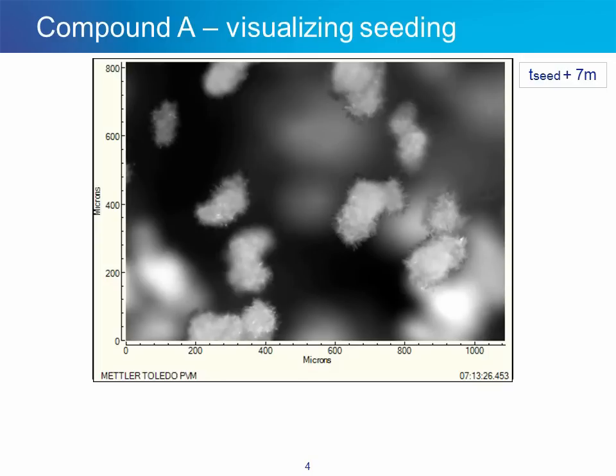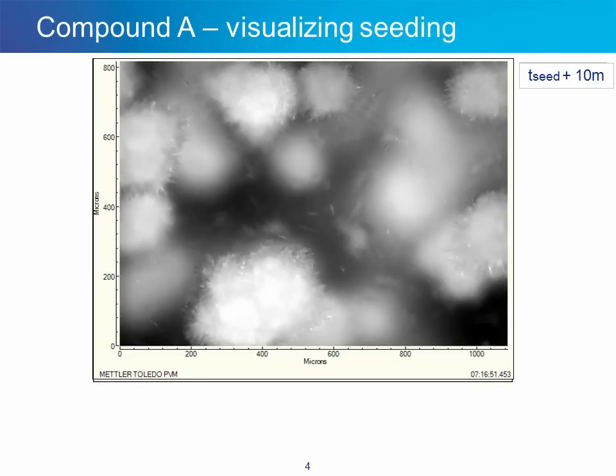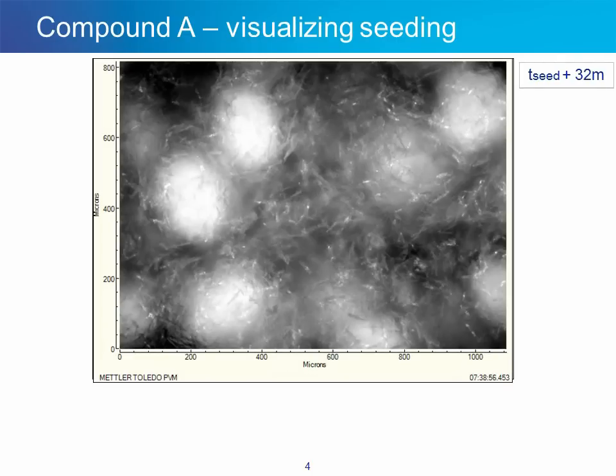Dendritic growth may be a word you could apply in this case. After 10 minutes, we begin to see these seed aggregates have grown even more, and now these small needle-shaped crystals are really beginning to grow from the aggregates and are actually beginning to shear off into the crystallizer itself. This is the beginning of a secondary nucleation event, occurring at about 10 minutes. Looking later in the process, after 30 minutes, we've actually ended up with a highly bimodal system — large seed aggregates in the background combined with a very high quantity of small needle-shaped crystals formed due to the secondary nucleation event.